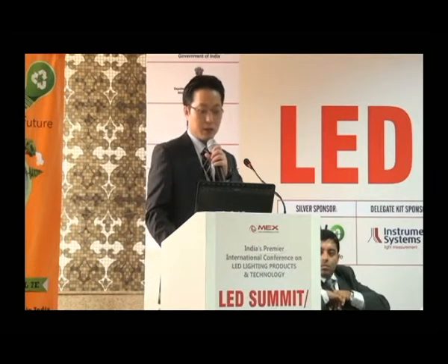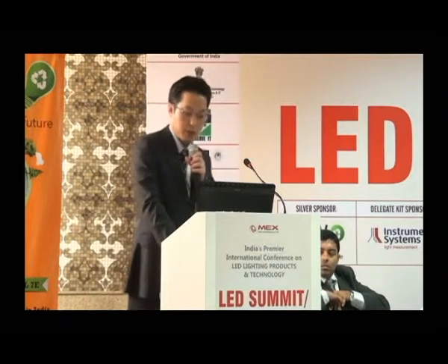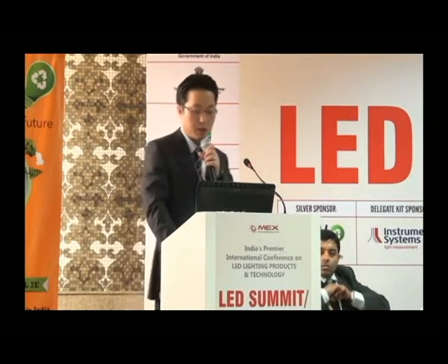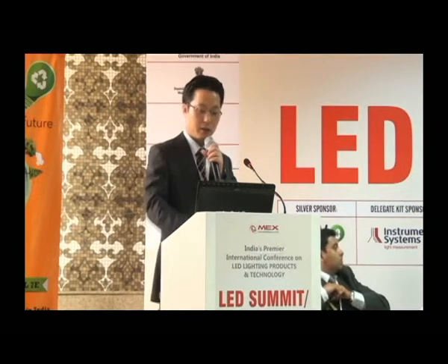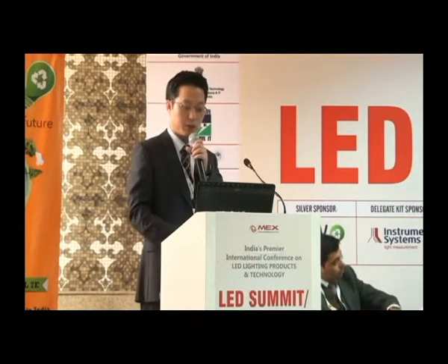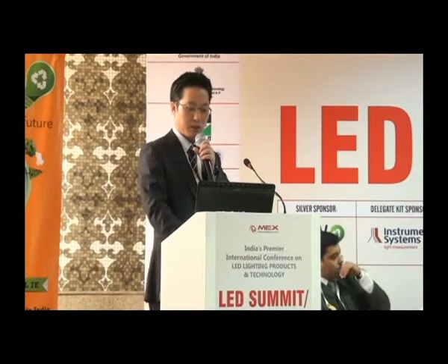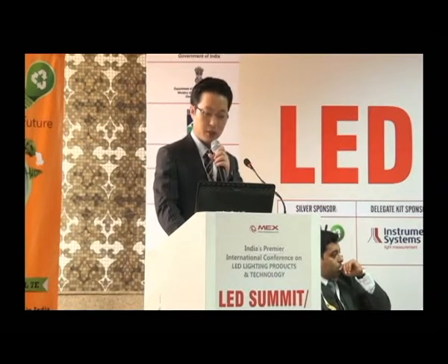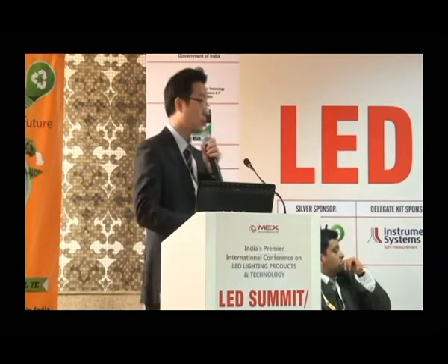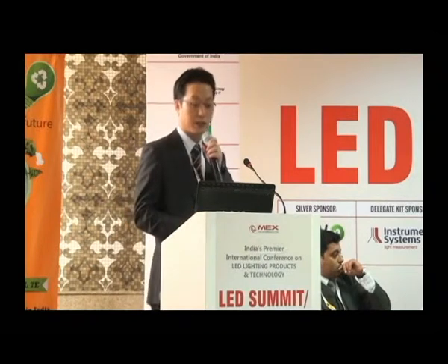And also this is mainly designed to produce LED lenses. It is separated by viscosity nowadays. You can use these 4 processes: stream molding, compression molding, transfer molding, and injection molding to make LED lenses or other optical devices.